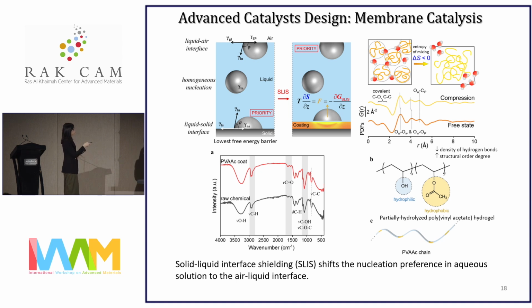And here shows the microstructure diagrams as well as atomic pair distribution function, and the observed decrease in the O-O distance of the hydrogel coating under compressive state is because of the decrease in the density of hydrogen bonds between the PVA system and the water network. And this confirms an enhancement in the structural order degree of the PVAc network and water molecules, then forming a water-permeated hydrogel, which repels any sort of approaching particles from a bulk solution. So with this, we have realized a novel solid-liquid interface shielding strategy, which shifts the nucleation preference now to the air-liquid interface, allowing us to create membrane right on the liquid surface.